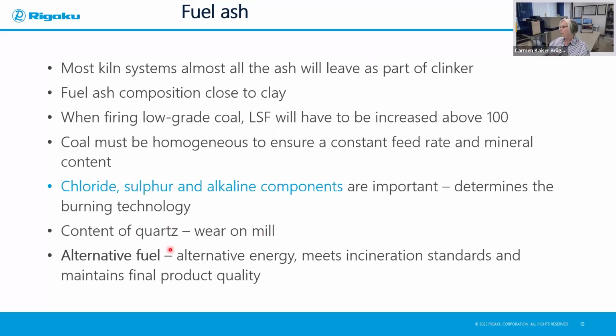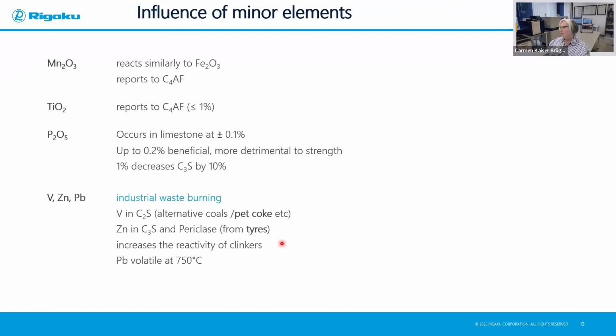So today we want to look at alternative fuels. This alternative energy that we use, other than what we have, which is the coal or the peat that we use, needs to meet the incineration standards, and it needs to maintain the final product quality. If we look at the influence of minor elements, for example, manganese can have an effect on the C4AF, which is the brownmillerite. So remember, the C is for calcium oxide, A is for the aluminate, and F is for the ferrite. The titanium will also influence the brownmillerite.